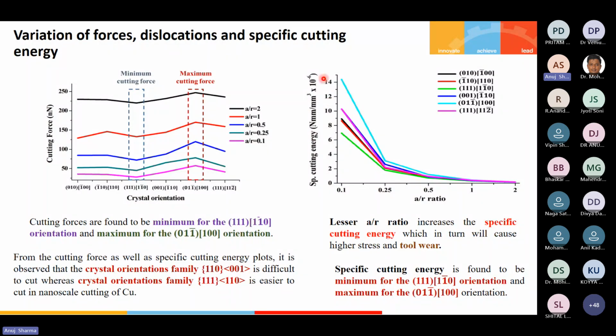Also, this specific cutting energy graph shows that at lesser A/R ratios the specific cutting energy increases, which means if the energy is more, the tool wear can be more at these lesser A/R ratios. It is also found to be minimum for the 111, 110 orientation and maximum for 011 and 100, similar to the cutting forces. With the help of these graphs, we can show that in copper it is very difficult to machine the 110 and 001 orientation, but easier for the 111 and 110 orientation.